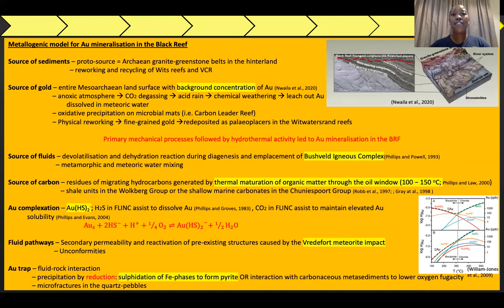Gold was transported as a bisulfide complex once it was dissolved. The presence of H2S in the fluid inclusions is known to assist in dissolving gold, while the carbon dioxide in the fluid inclusion is said to assist in keeping the gold in solution. The geological catastrophe of the Vredefort meteorite impact caused secondary permeability and reactivation of pre-existing structures, which allowed hydrocarbon migration and remobilization of fluids which have been circulating in the basement due to the Bushveld Igneous Complex, and this carried gold and other ore constituents. The erosional and angular unconformities also play a major role in directing the flow of fluids, which accounts for elevated gold concentrations at areas where the Black Reef is in contact with the Wits and the VCR.